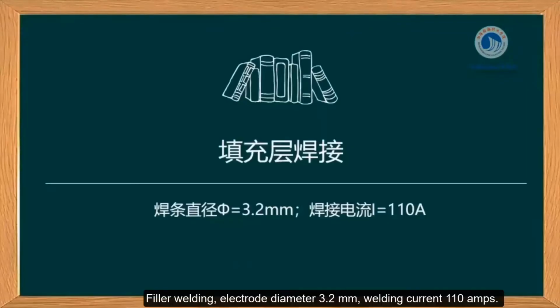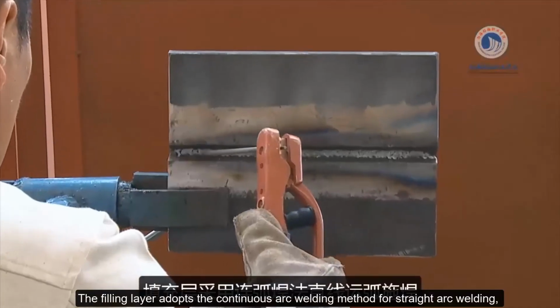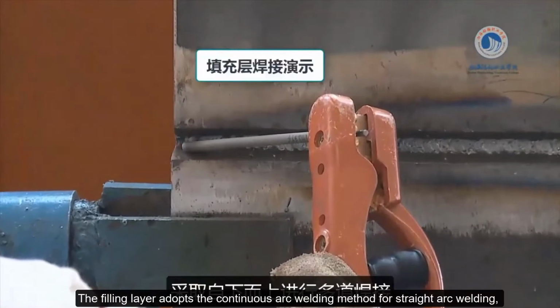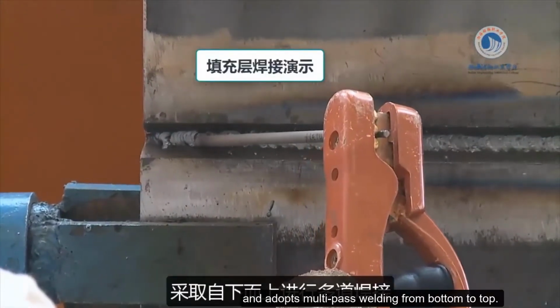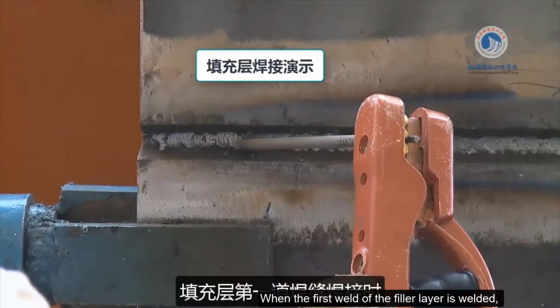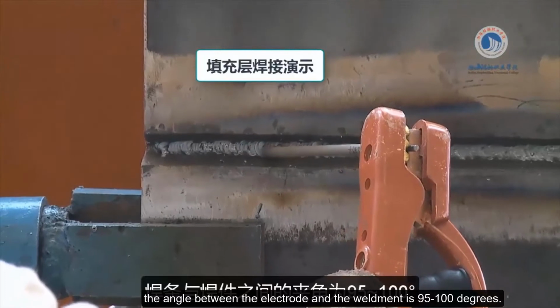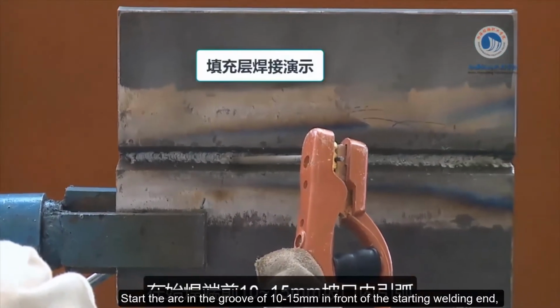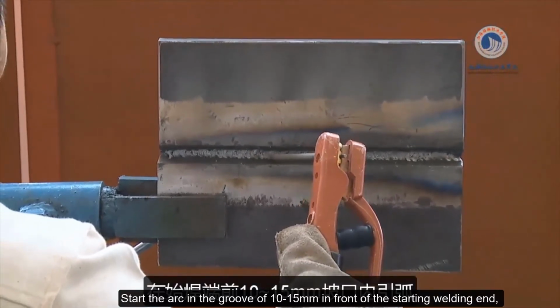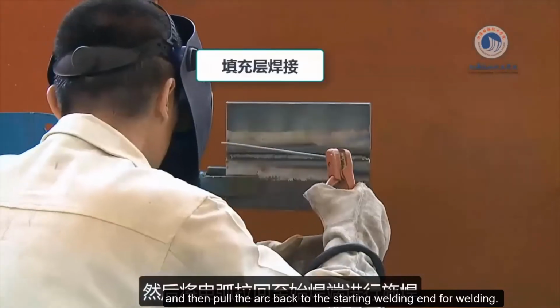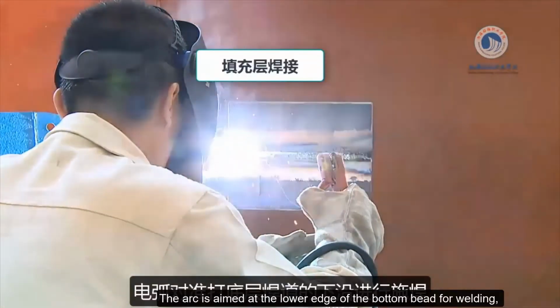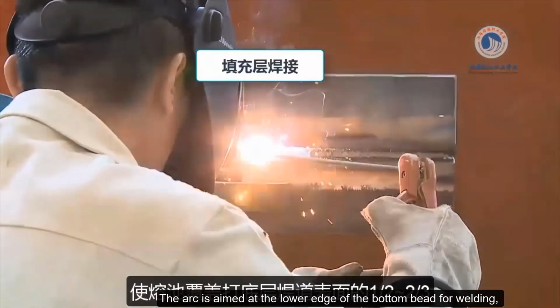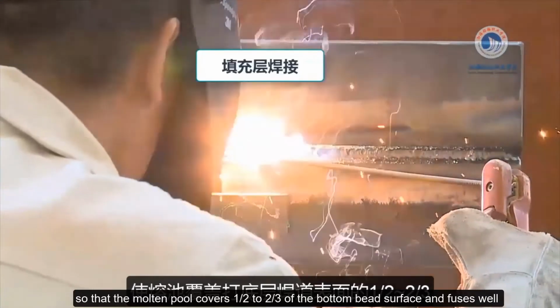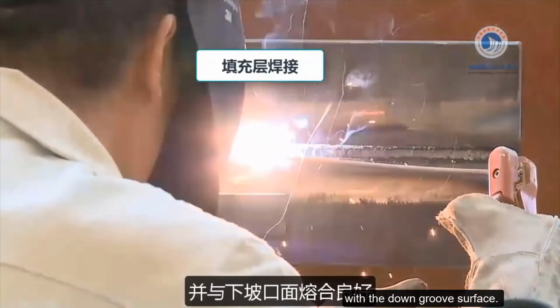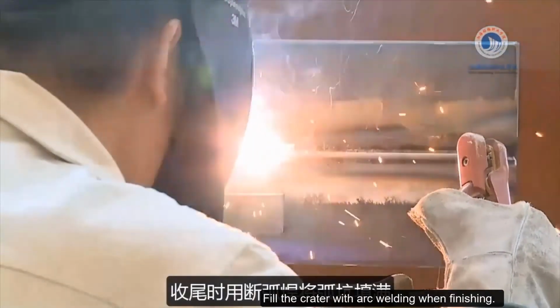Filler welding, electrode diameter 3.2 mm, welding current 110 amps. The filling layer adopts the continuous arc welding method for straight arc welding, and adopts multi-pass welding from bottom to top. When the first weld of the filler layer is welded, the angle between the electrode and the weldment is 95 to 100 degrees. Start the arc in the groove of 10 to 15 millimeters in front of the starting welding end, and then pull the arc back to the starting welding end for welding. The arc is aimed at the lower edge of the bottom bead for welding, so that the molten pool covers 1/2 to 2/3 of the bottom bead surface and fuses well with the down groove surface. Fill the crater with arc welding when finishing.